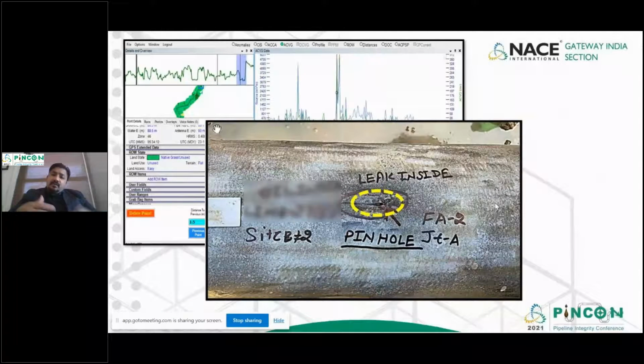After we removed the coating in that particular site, we actually found a leak, and we had tested this with bubbles to see that the leak was incoming. I mean outgoing, sorry, it was outgoing in that particular case. We actually stopped a catastrophe in that area because we found a leak by using indirect inspection technology. That is quite something, because again, I would like to reiterate, we are not supposed to be finding leaks through indirect inspection technologies.